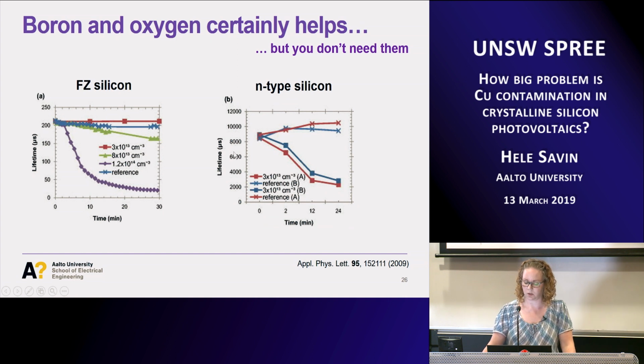minority carrier lifetime, so if we are in several microseconds, then we start to see also the copper LID. So if we put copper, the spots start to appear in these wafers as well. But same conclusion as for the oxygen. So you really need to have, I mean, you don't need oxygen, you don't need boron, but if you have them, then copper LID is much stronger.